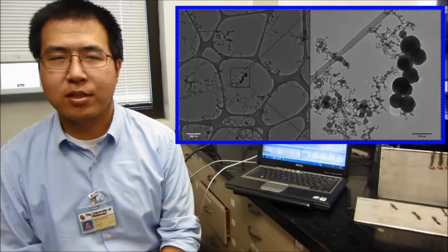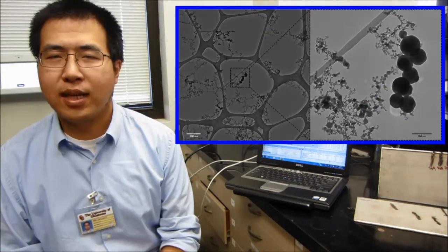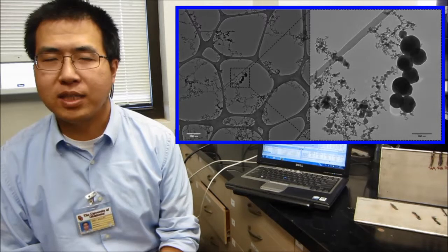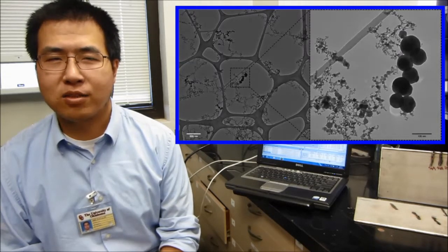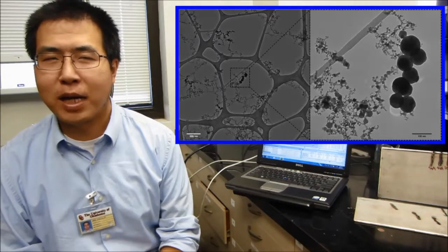The TEM images confirm the existence of nanoparticles in the cutting fume. There were chain-like agglomerates formed from the coagulation of the primary ultrafine particles. There were also large spherical particles formed from the coalescence of the metal particles.